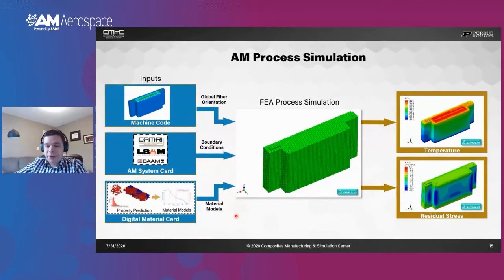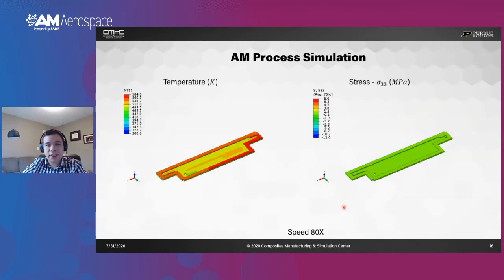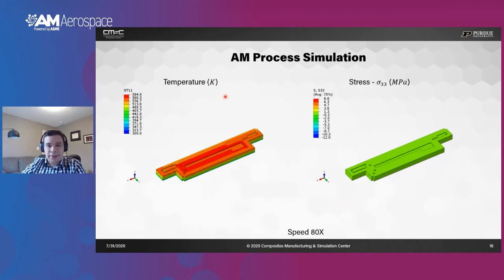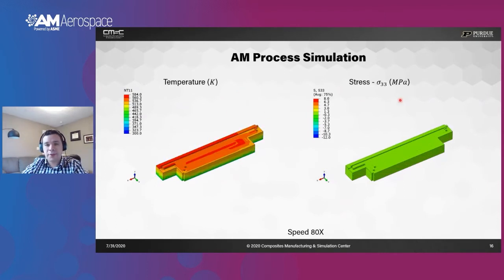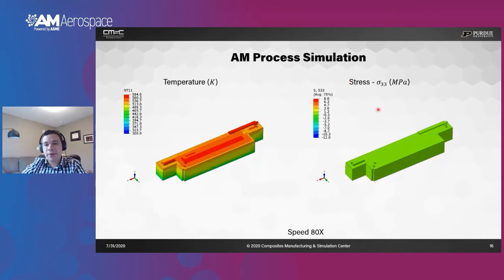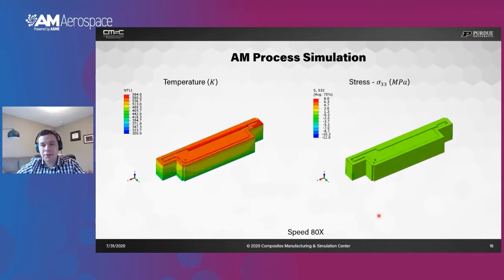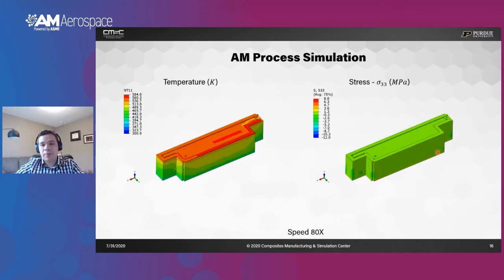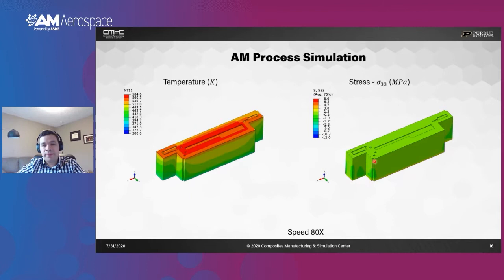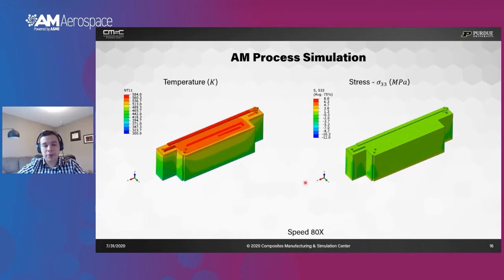So now looking first into the process simulations. As inputs, we need the machine code that was output by the slicing. We just select our system card and the material card, and we can perform the 3D printing simulation. We can see an example of the simulation results in here. On the left-hand side, we can see the temperature. On the right-hand side, we can see the stresses. In this case, the stresses are in the stacking direction. We are concerned about the stresses that might develop during the printing process and cause the part to fail or delaminate during the printing process.